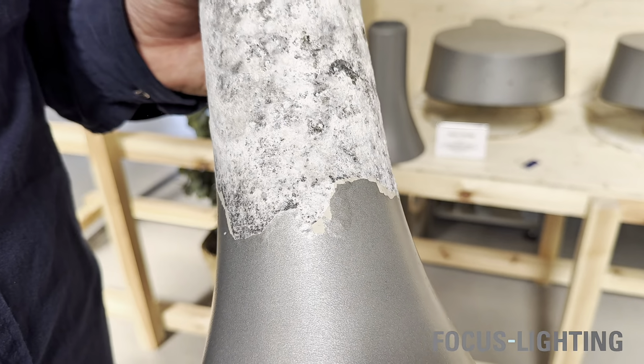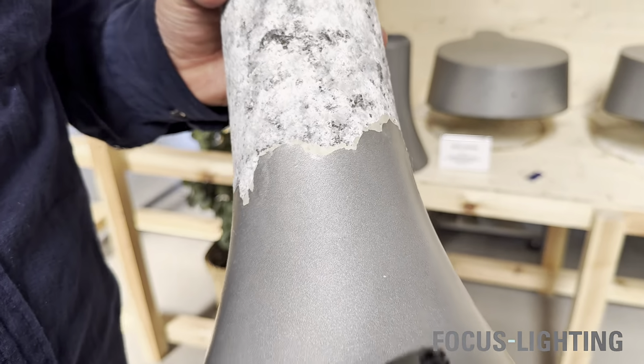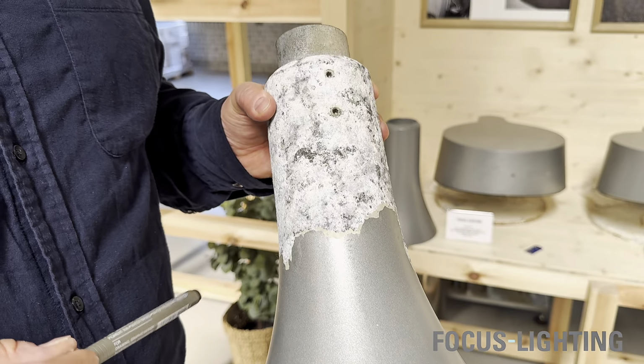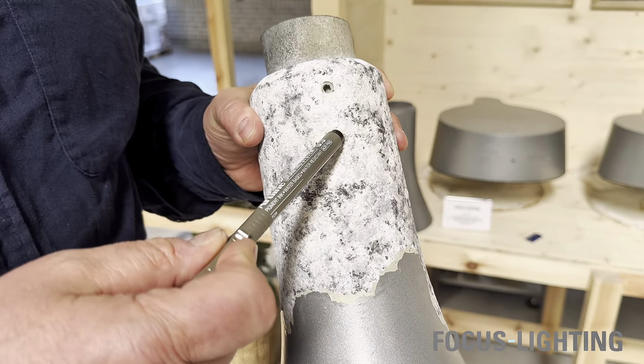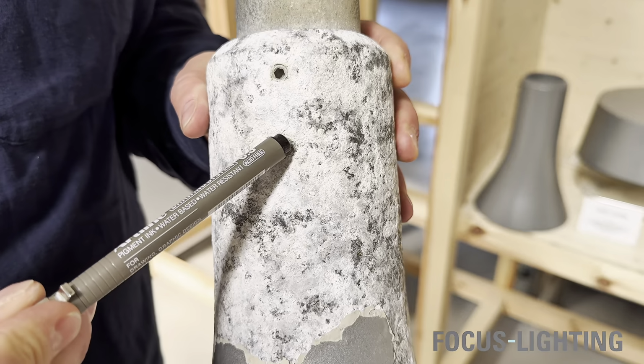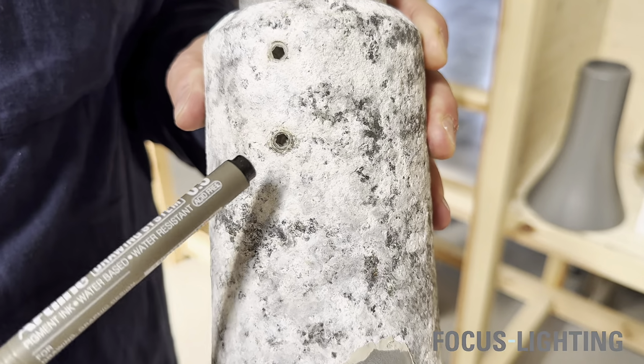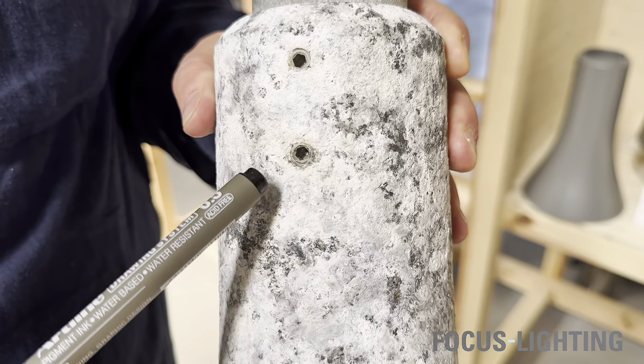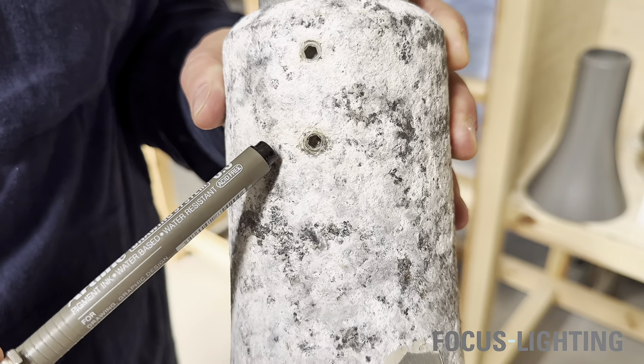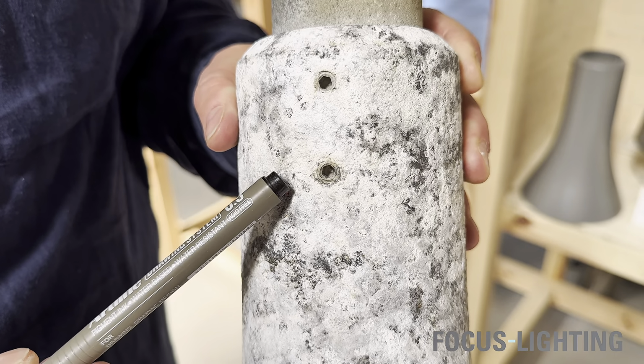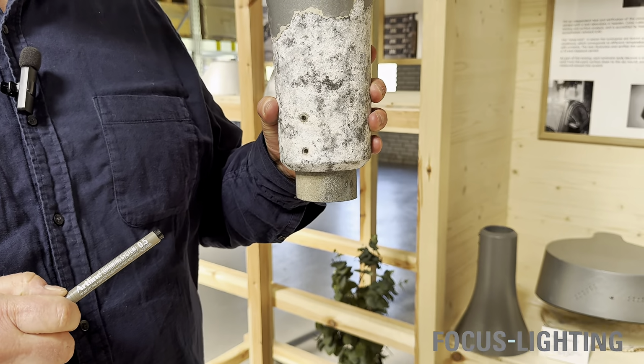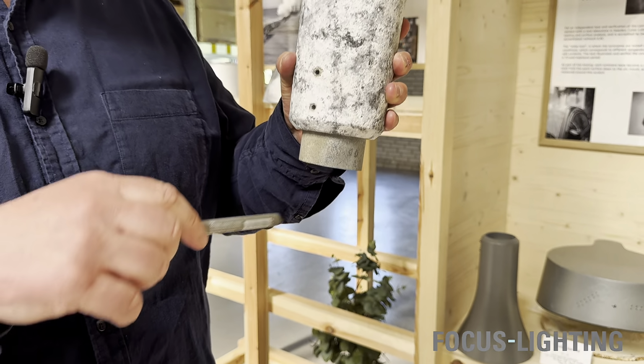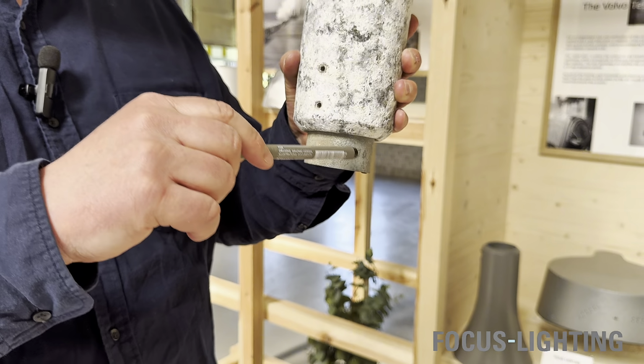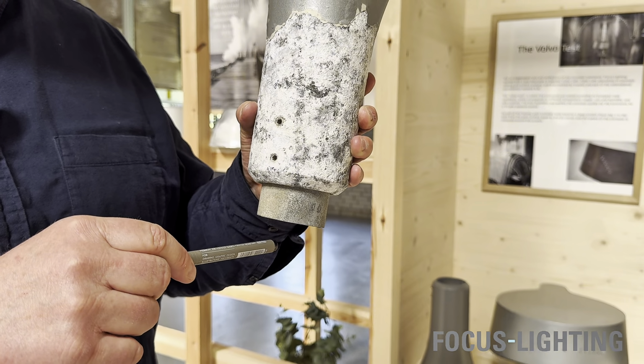And another thing that you would also have on this luminaire is actually galvanic corrosion. Here you see two screws that are mounted through onto the pole. These are made of stainless steel and they are corroded here in this case with the aluminum housing. In order to remove this housing and the luminaire from the pole, we actually had to cut the pole. So this is a part of the pole which you see here.